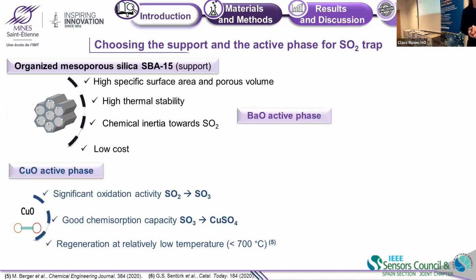And for the active phases, we chose two, in fact. We chose copper oxide because we know that it has a significant oxidation activity for SO2 to SO3, and then a good chemisorption capacity from SO3 to copper sulfates. And regeneration at low temperature is also possible.